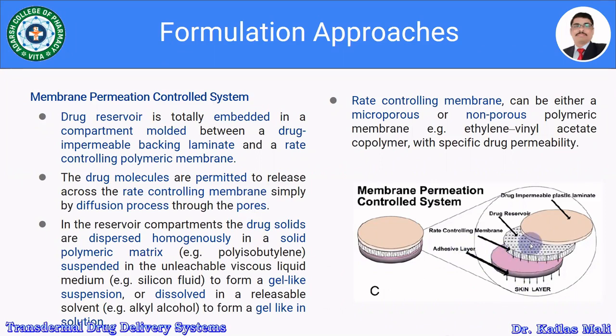In the reservoir compartment, the drug solids are dispersed homogeneously in a solid polymer matrix, for example, polyisobutylene, or suspended in an unleachable viscous liquid medium, for example, silicone fluid, to form a gel-like suspension, or dissolved in a releasable solvent, for example, alkyl alcohol, to form a gel-like solution.